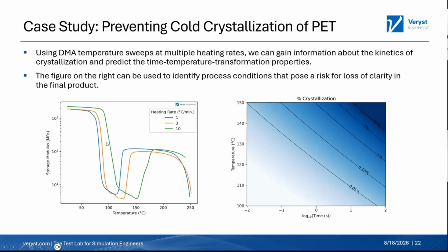Basically, the glass transition temperature will shift up at higher heating rates, as well as the nucleation and growth kinetics of the PET will shift to higher temperatures because it's fundamentally both kinetic processes. And so you can use data like this to calibrate a kinetic model for the time temperature transformation of the PET from its amorphous to its crystalline state.